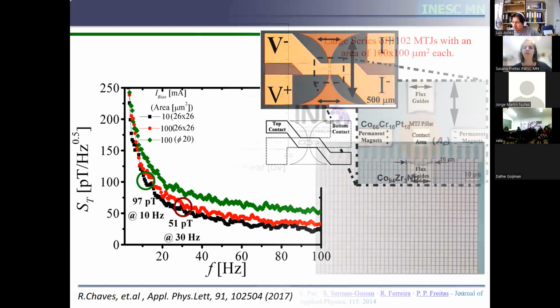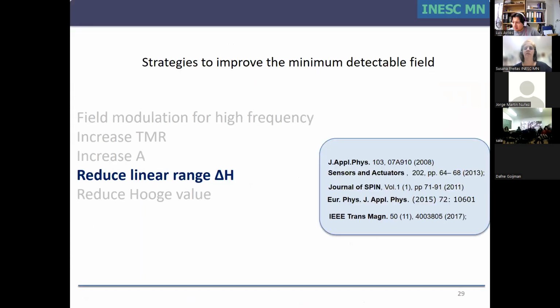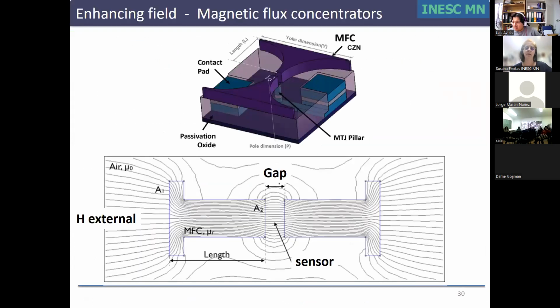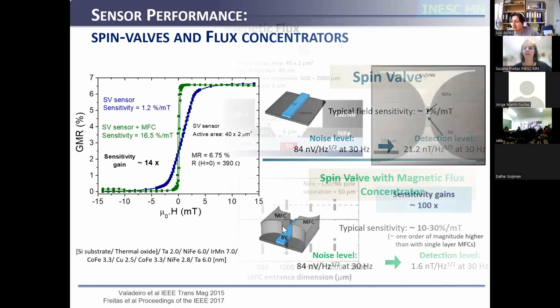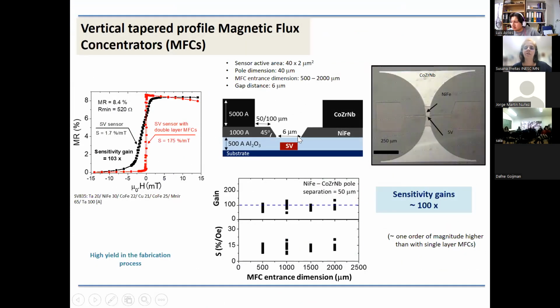Typically a flux guide has this shape, either flat or, if you do it better, with a trimmed edge, correct? This is what we normally expect from a flux concentrator. In that case, the issue was that we had a round profile in the sensor, so it was not easy to have a sharp edge, and we don't want different separations. So we should also have a round profile for the gap. It's not usual, and normally we don't do it like that. Okay.